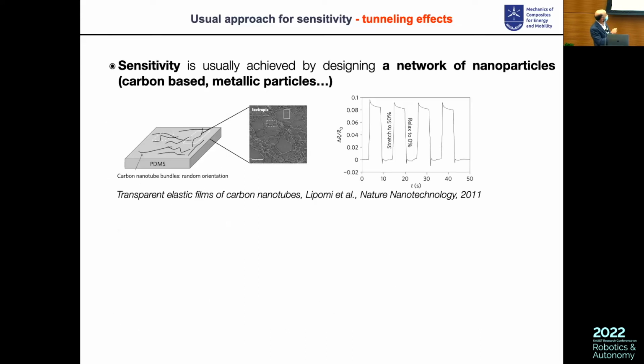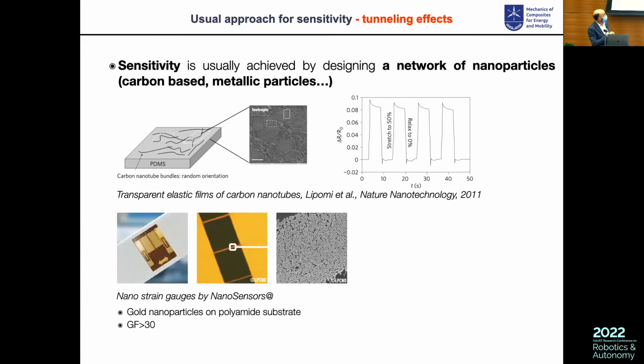It has been used, for example, as a coating of nanoparticles on PDMS, on different kinds of silicones, right? Here you have a paper from 2011, where they show that if you make a coating of nanoparticles on a PDMS substrate, you get a change in resistance when you extend it. That exists. You have a piezo-resistivity, but it's very small here. That means you get a gauge factor that is very small. You get a big stretch, but a very small gauge factor.